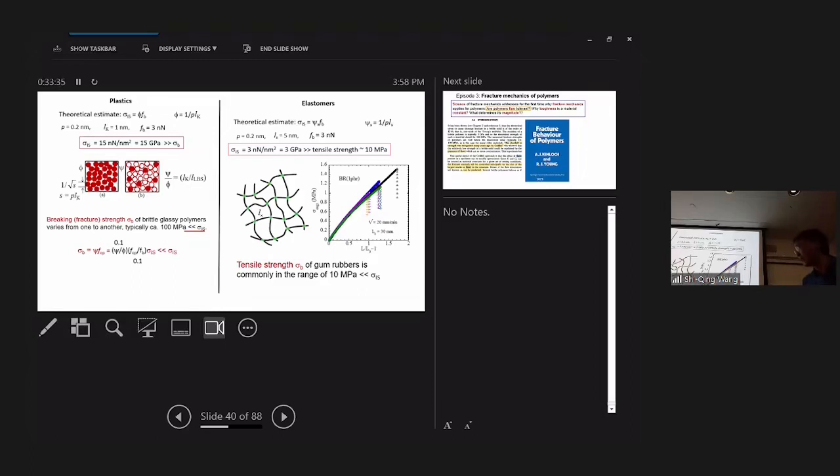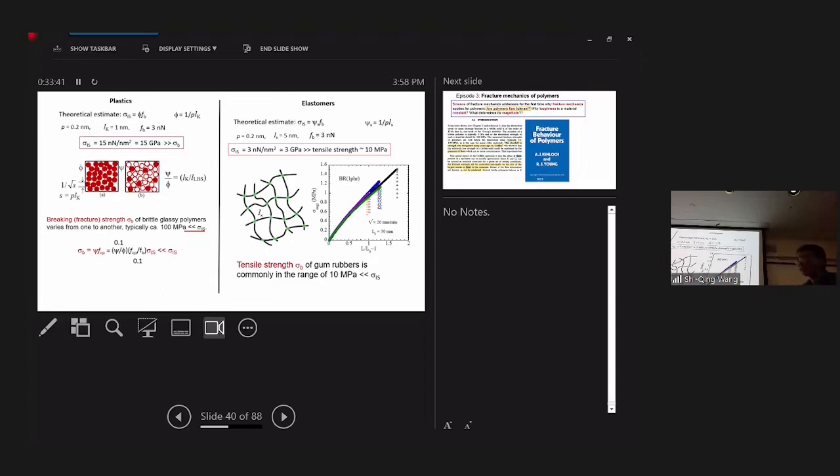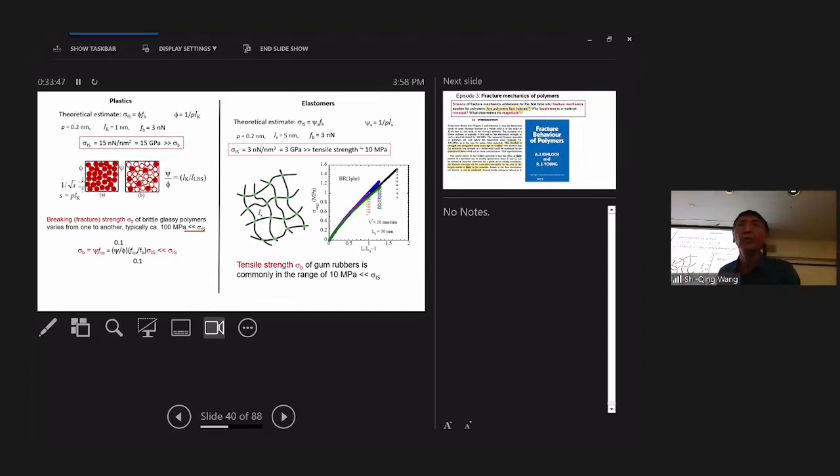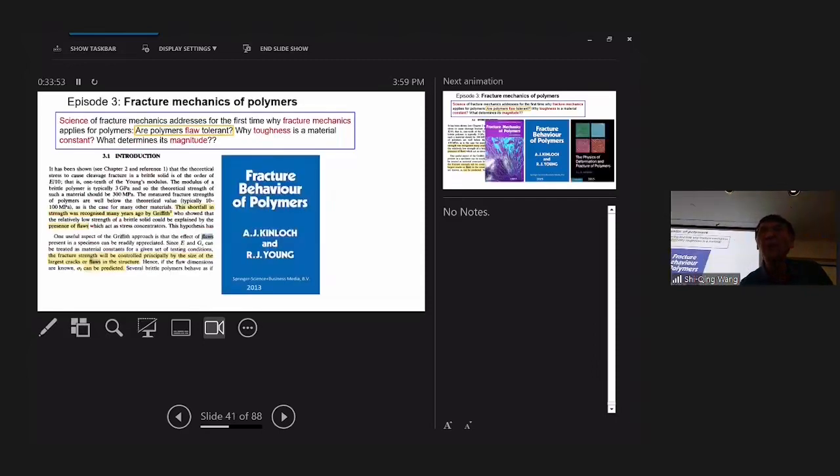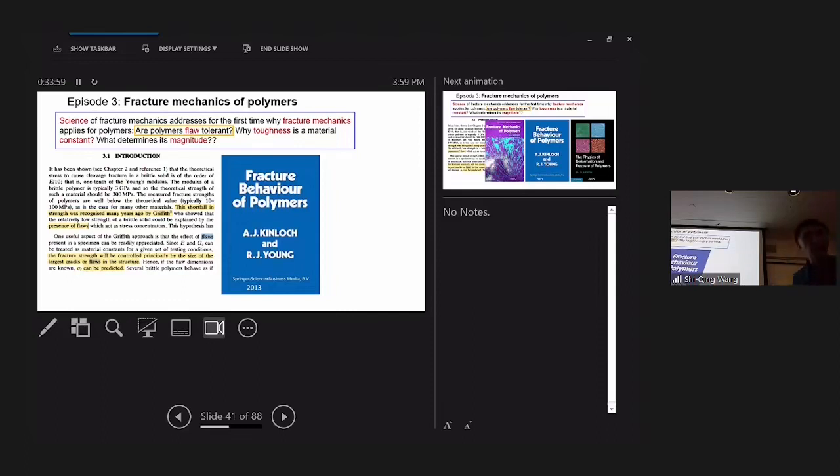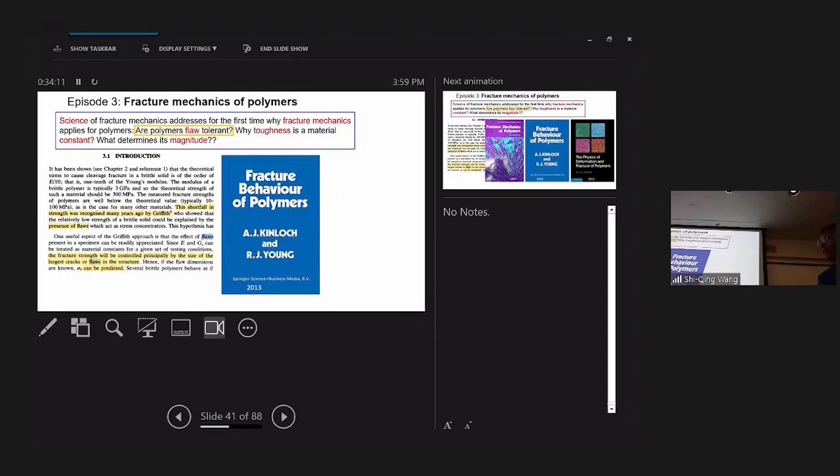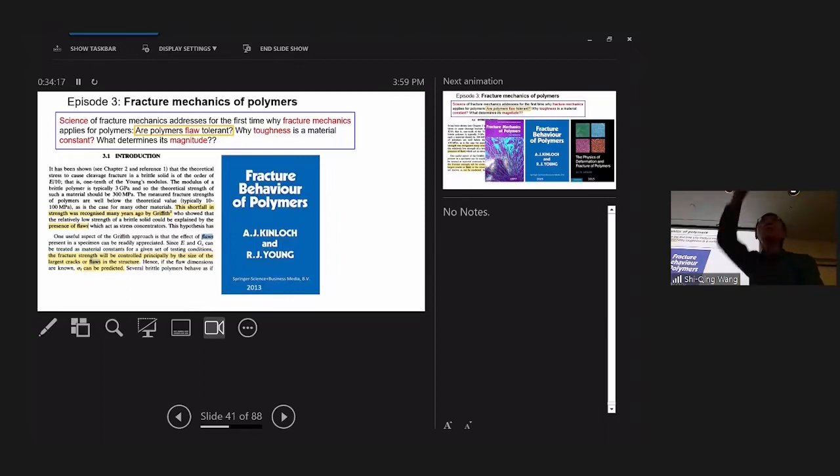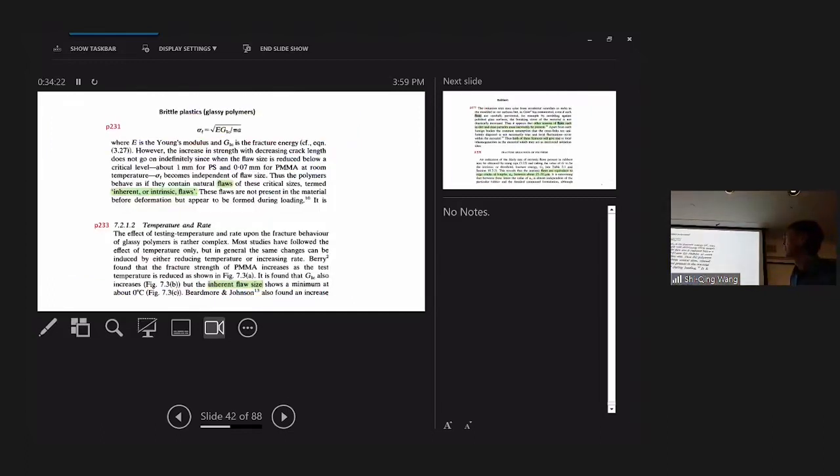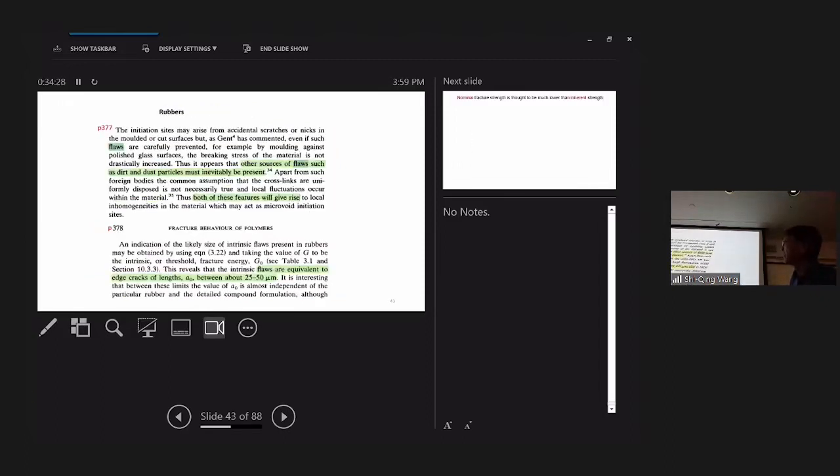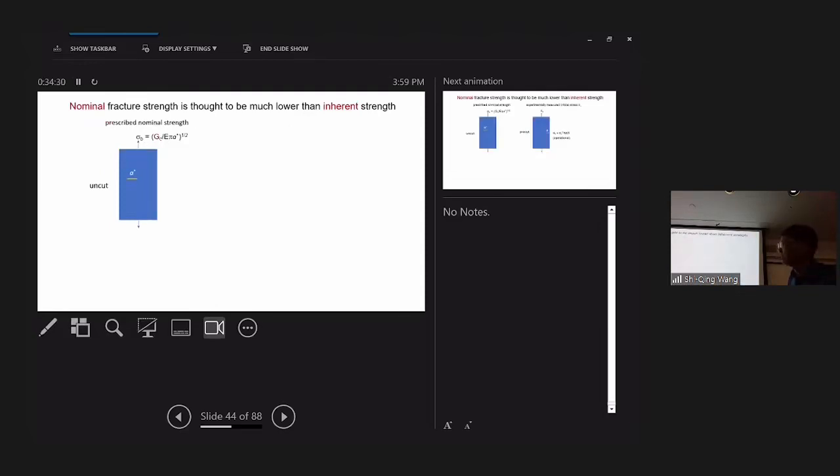What concerns me is this so-called dual yielding. Take your high density polyethylene. If the crystallization is too much, the high density polyethylene is not ductile. Whereas linear low, which does not have a lot of crystallization, it yields beautifully. Polycarbonate yields or not, depending on how you have produced the morphology that disrupted or not disrupted the chain network. So anyway, there are many parameters including temperature, drawing rate, morphology, and different polymers behave differently. It's a mess here. I just want to show you one example where we have some success.